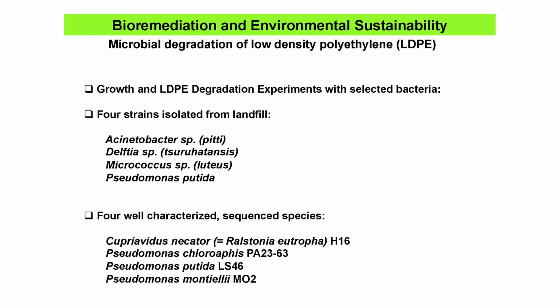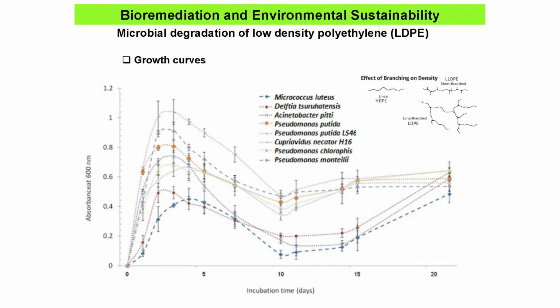And we had 4 well-characterized species in our lab that make PHAs, but are also ubiquitous soil bacteria, and they're known to be hydrocarbon-degrading bacteria. So we thought we would try it, because if we find something, we could correlate it with the genome, because that's what we do, right? So what we found, what Zara found, was that what she did was actually take the bacteria and cultivate them in pre-cultures with mineral oil. So mineral oil consists of alkanes, linear hydrocarbons that have single bonds between each carbon. So she grew it on hydrocarbon first, and then over time reduced the amount of hydrocarbon, increased the amount of polyethylene, and these are polyethylene powder, essentially. And so until it was growing on 100% polyethylene.